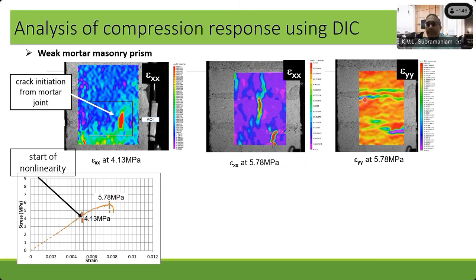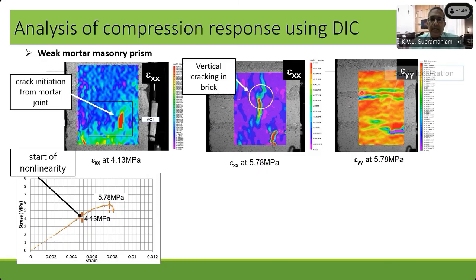The other thing we observe is that there is a localized failure that happens. The brick, which is in a state of triaxial compression, compresses here, and it experiences localized compressive failure. It crushes over there. So there is a crushing mode of failure that happens in the brick, and there is splitting perpendicular to the joints that we observe in these masonry assemblies.